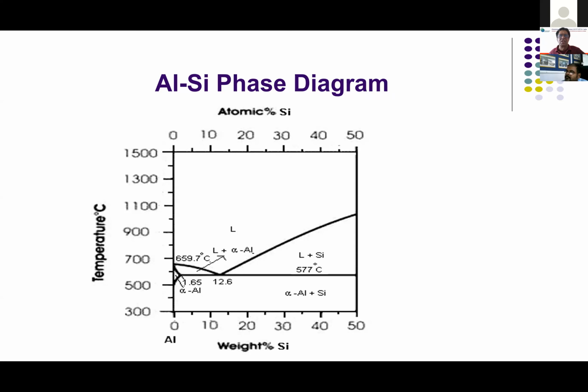Whereas in the conventional Sklenar furnace or rotary furnaces, when you make an alloy, the silicon going into solution is to be ensured. The operator or the shop floor engineer who is standing near the furnace has to see that the silicon goes into solution properly. That is why I normally recommend, when the customer gives a range of 11 to 13, stick to below 12, stick to 11.5, below the eutectic point, which will help you ensure that you have only alpha aluminium, not pure silicon present in the alloy.